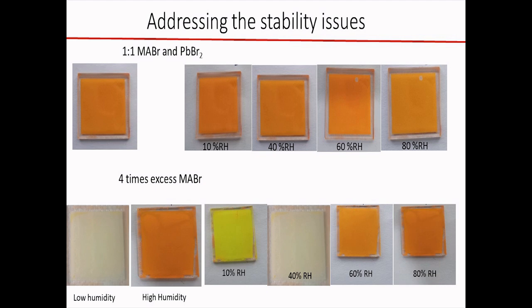Serendipitously, what we found was that when we take this film and go outside of our lab - inside the lab the humidity is very low, something like around 40% - but when we went outside, the film turned its color to something very dark, more or less similar to the methylammonium bromide lead bromide that we had initially prepared.